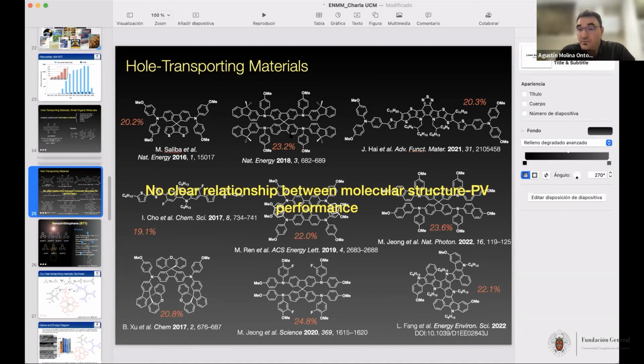I don't know why Spiro performs so well in comparison with other molecules, but you can introduce just two different TPAs or diphenylamines, and the molecule will work exactly the same, very well. In this case, they are using a very congested, big central core. Maybe the lone pair of the sulfur can interact with the perovskite, which is a very important parameter, and can enhance the hole extraction of the molecule. So everything has its influence. Not by adding more TPAs will you have more efficiency, but if you have a good design, you can obtain a good efficiency. Yeah, of course.